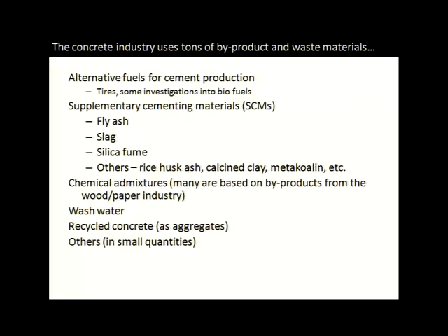So I mentioned that concrete is a very forgiving material. We can put a lot of recycled materials into it, and it can take on a high recycled content. One of the main ways that we can improve the sustainability of concrete right now is increasing the use of supplementary cementing materials. So I won't talk about all these other areas, but when I say supplementary cementing materials, we're talking about materials like fly ash, ground granulated blast furnace slag, and silica fume. Those are all byproducts of other industries that would otherwise be landfilled, but we can put them into concrete in varying dosages, fly ash and slag being the most forgiving, and that we can put probably 30 to 60% of those materials and replace a portion of the Portland cement and actually end up with a better material and a better product because of that.